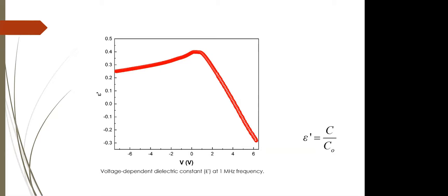After 0.89 volt, a rapid decrease is observed. This is due to the special case of interface states. When the forward voltage increases, the capacitance value reaches its maximum value and then decreases rapidly and takes a negative value in the accumulation region. Therefore, a similar situation occurs in the dielectric constant values.